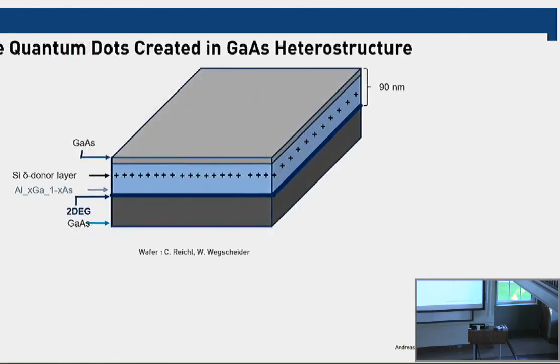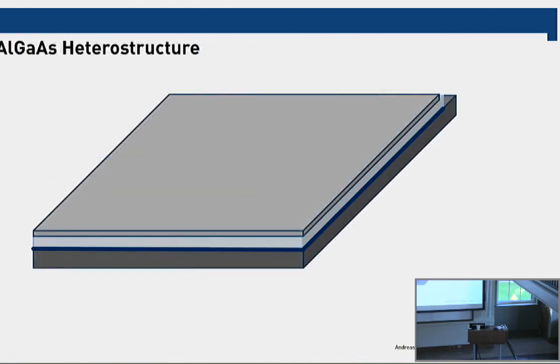Okay, so just very briefly for all of those who don't know how these quantum dots get made. We start out with a gallium arsenide, aluminum gallium arsenide heterostructure that Werner Wegscheider grows for us in one of his MBE machines. You start out with a gallium arsenide substrate, you put the aluminum gallium arsenide on top of that, you introduce a doping layer that creates charges, and that then creates this two-dimensional electron gas at the interface, and there's a capping layer on top of your substrate. And then you're trying to structure the electrons in this two-dimensional electron gas by applying voltages to top gates.